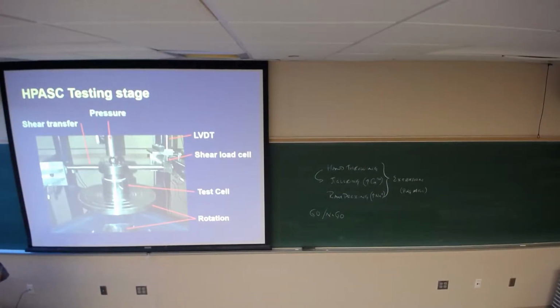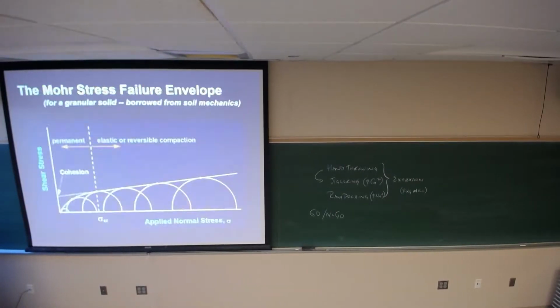It's really fascinating how it works, in that you actually get a shear failure in the material. And the first device like this that I built was for catalyst support extrusion, really fascinating data. And then when I got to clays, though, I actually had to serrate the platens so it gripped the clay. Otherwise, the clay slid, and you get slippage, and you don't get the right response. So what happened is that you would put the clay in, and then as you would shear it, it would fail and shear, and you're measuring the shear behavior, and you can independently change the load, you can change the rotation rate.